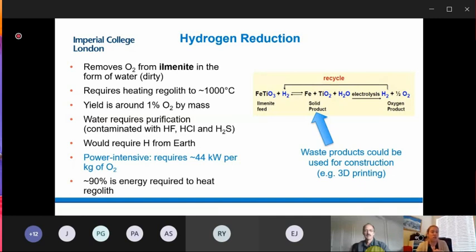So the way that hydrogen reduction works is that it targets the ilmenite in the regolith. I mentioned there were two different regions on the moon: a high titanium mare region and a low titanium highland region. So it targets the ilmenite in the regolith at around 900 to 1,000 degrees C to produce water, which can then be electrolyzed to produce hydrogen and oxygen. The hydrogen can be recycled. However, we would need to take hydrogen with us in the first place. So we can already start to see some of the challenges here.